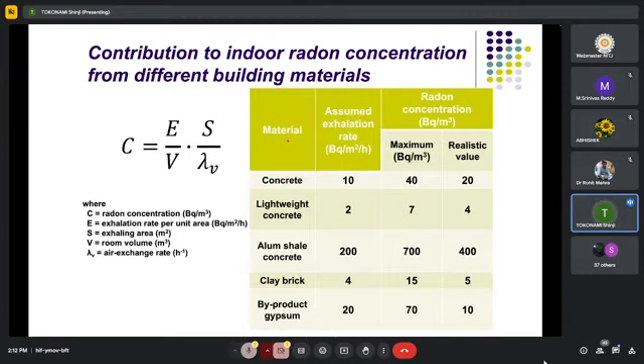Here are the various materials. Concrete, we assume the exhalation rate of 10 becquerel per square meter per hour. The maximum radon concentration will be 40 becquerel per cubic meter. Realistic value 20. Lightweight concrete, when we assume the exhalation rate of 2, the radon concentration will be 7 as maximum, 4 as realistic value. Alum shale concrete, if we assume the exhalation rate of 200 becquerel per square meter per hour, the radon concentration goes up to 700 becquerel per cubic meter, and realistic value is 400 becquerel per cubic meter.